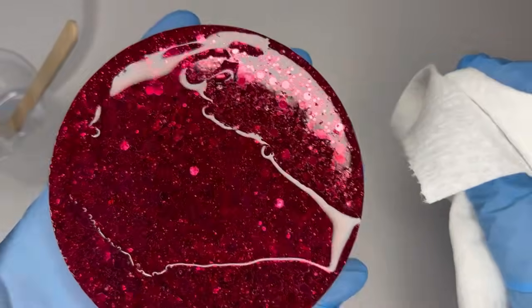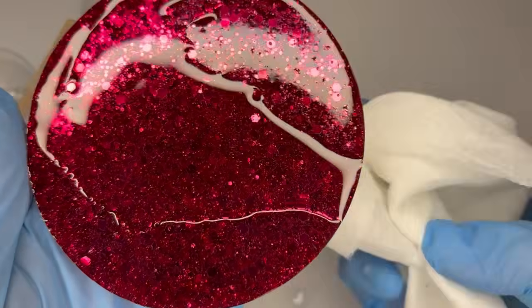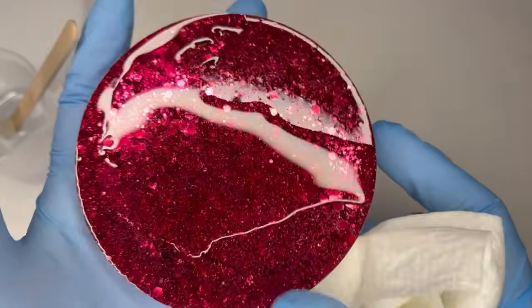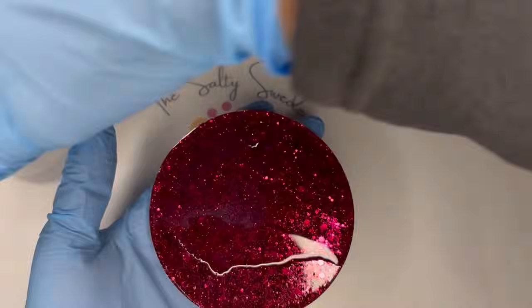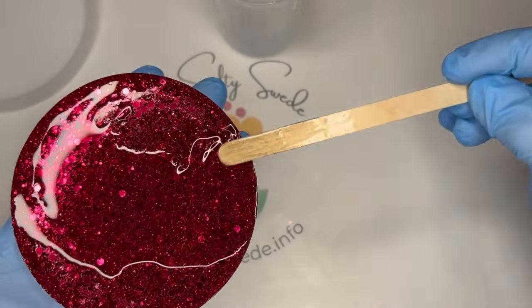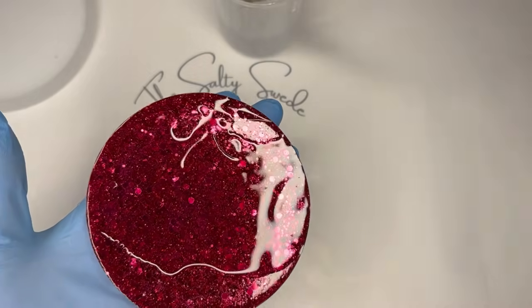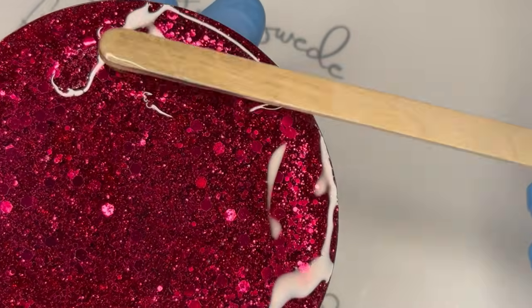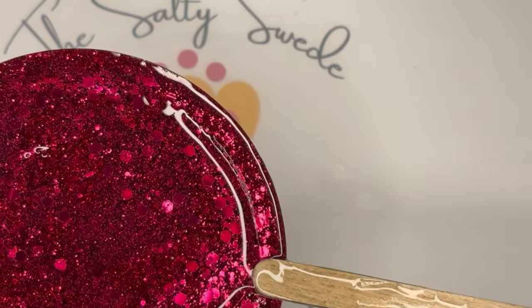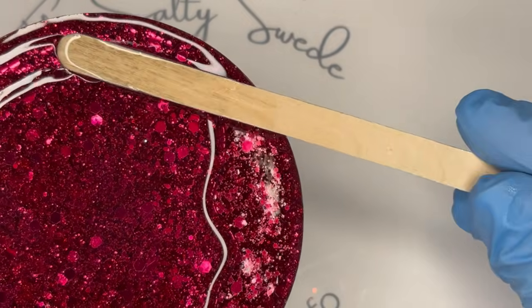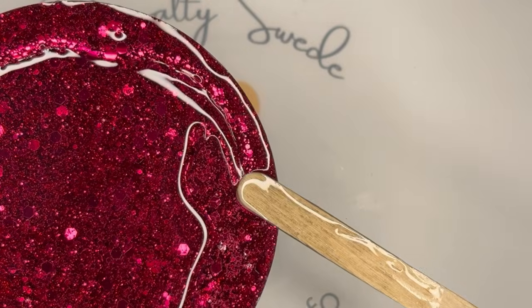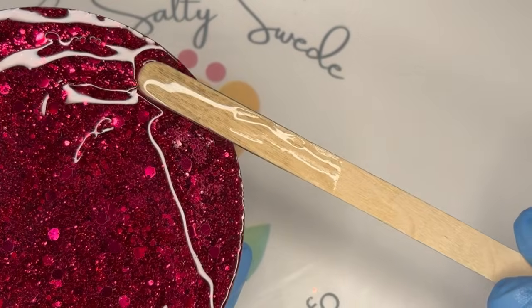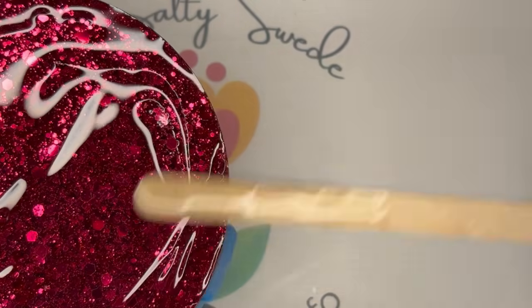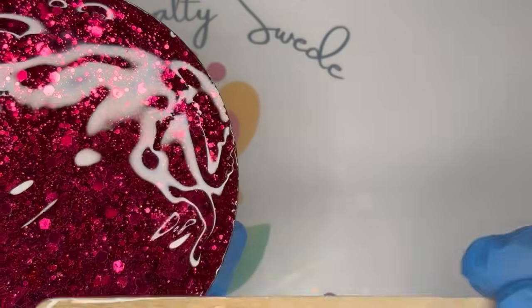I've sped up the video, but know that this technique is very time consuming, so take the time you need to be successful. I'm going to continue around the coaster, getting the resin on every surface of the top. You'll see that the resin is shrinking away in some areas. That's called fisheye. This can happen for many reasons. Sometimes it's due to temperature, sometimes there's something on the surface of your resin like dust or moisture that keeps it from sticking. It can also be the type of resin you're using.